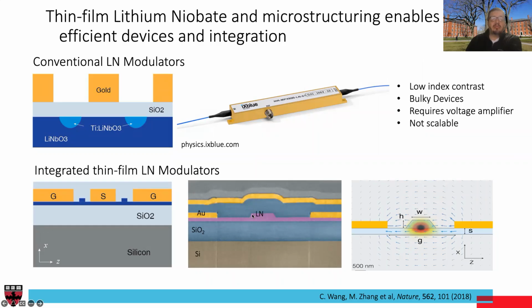This actually has much better optical confinement and much better overlap between optical and RF fields, which allows you to have very high electro-optic efficiency. Therefore the drive voltages, or as we call them VPI in this business, the voltage required to change the phase of one of these waveguides in a Mach-Zehnder interferometer out of phase with respect to the other waveguide, are low, significantly lower than in the case of these conventional devices.